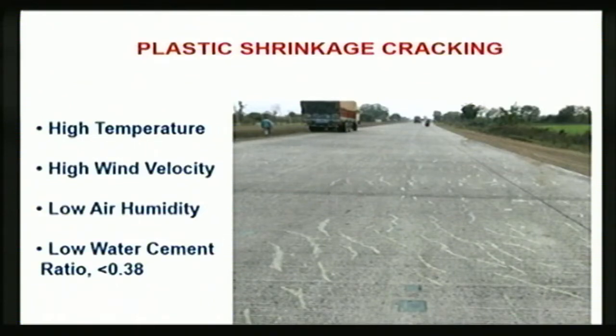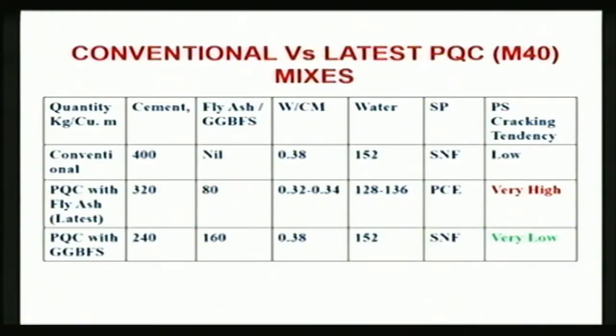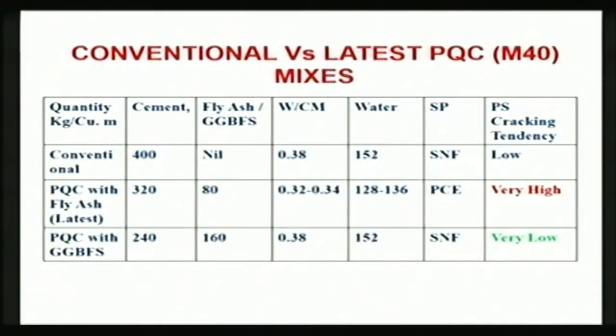These are the same kind of plastic shrinkage crackings. And if you can see there, if you use GGBFS, your tendency of plastic shrinkage cracking will be very low. If you use fly ash along with the reduction of water cement ratio, you will have a very high tendency. For the normal concrete, it may occur, but the tendency will be low.